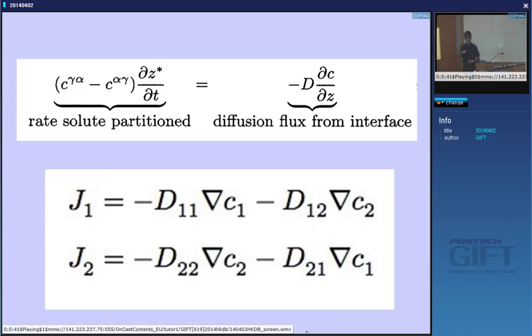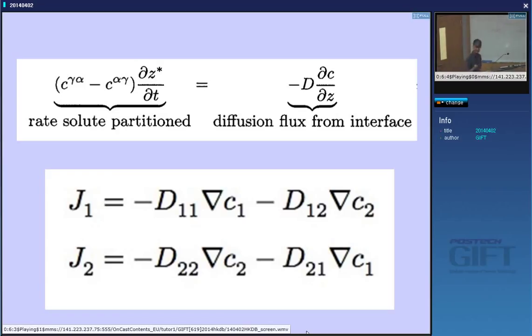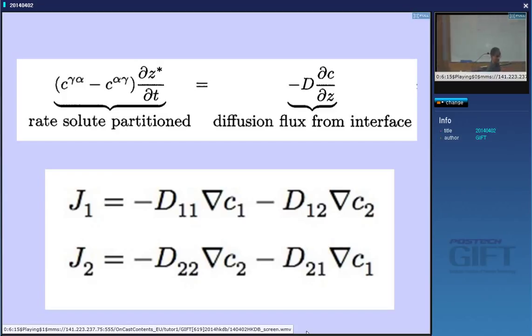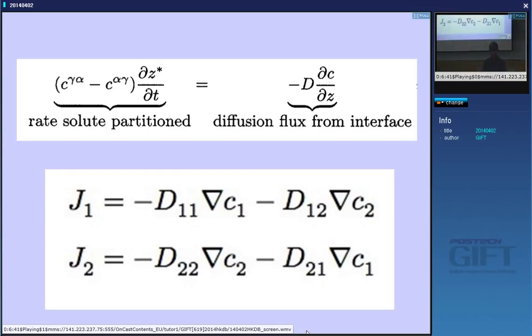The alternative scenario is that you make the gradient of manganese extremely steep. How can I make it steep? What is the area under that triangle controlled by? Remember we had a mass balance equation — it's the total amount of solute that is thrown out. So if we reduce the amount of solute that's thrown out, that gradient will become steep. How can I reduce the amount of solute thrown out? If C-αγ is approximately equal to C-bar, then the area under that triangle decreases.